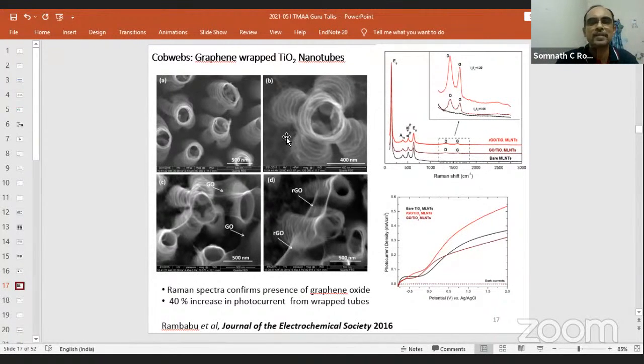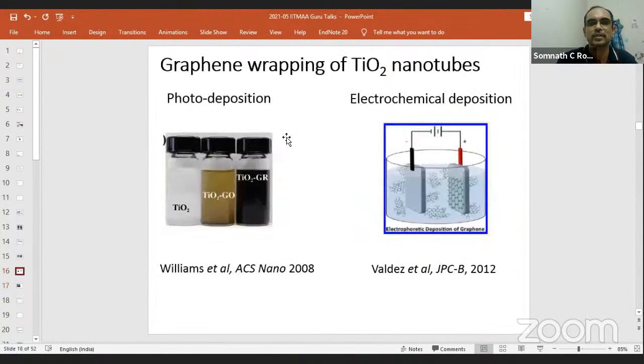So when they are well separated, we found this structure here. Then we had to run two different techniques. One is called photo deposition. In photo deposition, what did we do? We procured a commercially available graphene oxide precursor, and then we dipped our nanotube material and shone light. Of course, this is not from our experiment. This was from a paper in 2008, but I'm just showing what they did. The first time they did photo deposition, they worked with TiO2 powder.